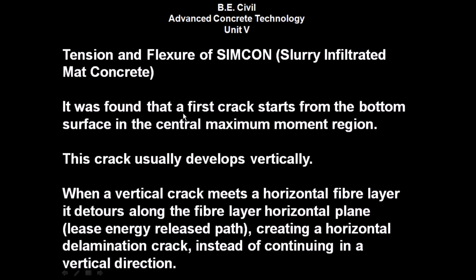It was found that a first crack starts from the bottom surface in the central maximum moment region. This crack usually develops vertically. When a vertical crack meets a horizontal fiber layer, it detours along the fiber layer horizontal plane, the least energy release path, creating a horizontal delamination crack instead of continuing in a vertical direction.